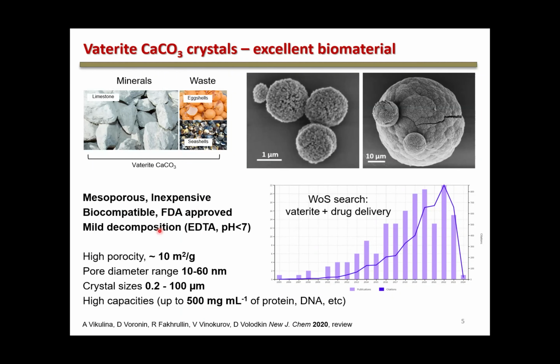So what is very important, what I like very much, is that the conditions to decompose calcium carbonate are very mild. This makes them applicable for fragile biomolecules, like many biofactors and especially large biomacromolecules. So you can get rid of calcium carbonate at slightly acidic pH in the presence of EDTA, for instance, or citric acid or other chelating agents.